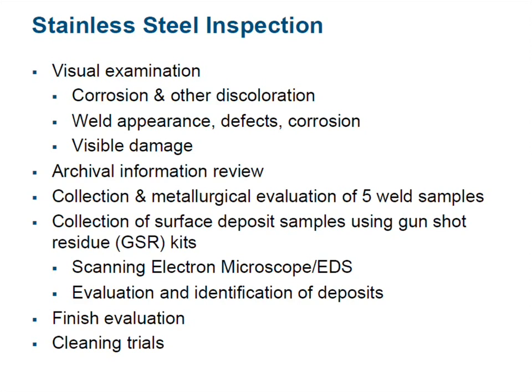We used GSR, those are gunshot residue kits. TMR has been using them for a very long time because you're able to collect fine particles from the surface that you would not otherwise be able to collect to evaluate without having to do anything destructive. Just as the police can determine if someone has a gunshot residue on their hands or collect fine fibers. Now you can use a scanning electron microscope to determine exactly what those are, which is what we did. We also looked at the finish, which will be discussed later, and there were cleaning trials.